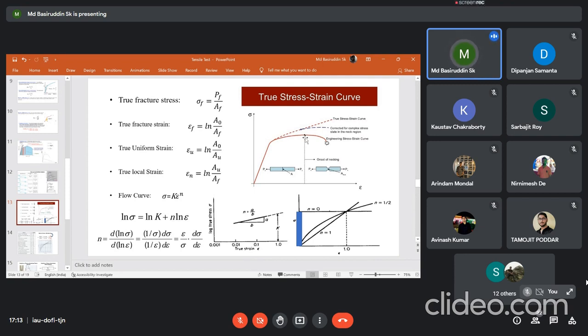That means the preferential deformation generally happens there, and therefore the whole gauge length will not take part in this elongation. Only the reduced part is taking part. So that is why you have to measure the cross-sectional area continuously, let's say at 5-second intervals, and then only will we be able to draw the true stress-strain curve till the fracture. But if we are unable to measure, then we can use some equations which give us quite approximately accurate values, not exactly, but quite approximately.